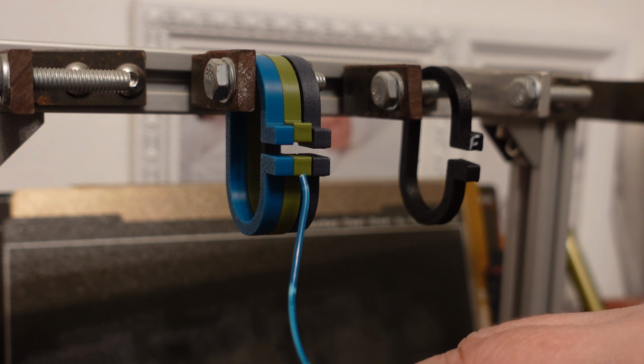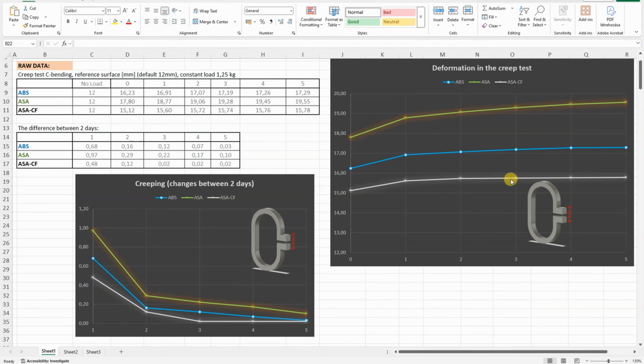on the regular ASA. On this graph we can see the deformation, the distance between two reference surfaces, and we can see biggest deformation on the ASA and smaller on ASA-CF, but the creeping is the difference between 2 days, and that's presented on this second graph, and we can see biggest creeping on the ASA and smaller on the ASA-CF. ABS is closer to ASA-CF, and basically after day 2 this became very minimal.